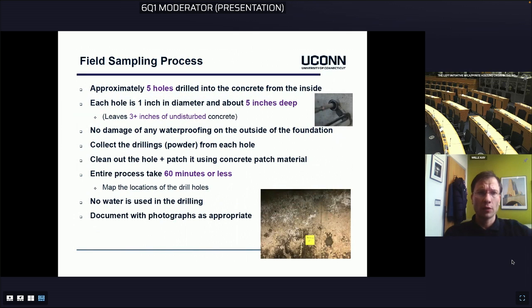We drill 5 holes in each foundation, about 1 inch in diameter and 5 inches deep. We do not compromise any waterproofing, so we do not drill all the way through the foundations. It takes about 60 minutes or less. We don't use any water. We patch the holes afterwards, and, as I said, within an hour we are out of the house again.